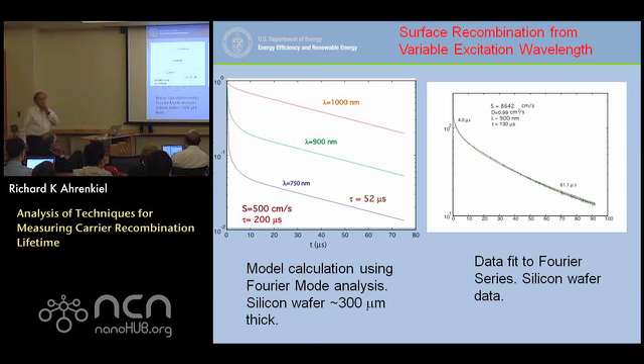Okay, surface recombination is another big issue. I showed you the silicon wafer that was immersed in iodine methanol, and we had the lifetime change by a couple orders of magnitude. So here's some calculations using a Fourier series model for the transient carrier concentration in a silicon wafer model calculation, all analytical, and we assumed a standard thickness, and we assumed some values of surface recombination.